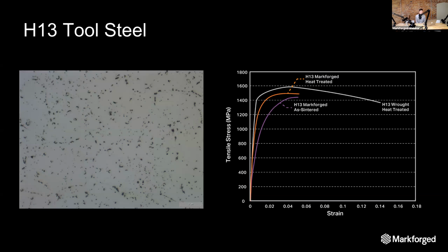So think molds. Overall, it's a material that reaches a Rockwell hardness of about 40 off our printer. It's hardenable through our established standards to 45 and theoretically up to 50 or 52. So it's a pretty hard material. It's not like A2 or D2, which you'll see up in the high 50s, maybe even the 60s range for Rockwell C hardness. But overall, it's a great material for injection molds, for wear tooling, for anything that needs a little bit more robust surface strength than 17.4. And so that's kind of where we're at on this.